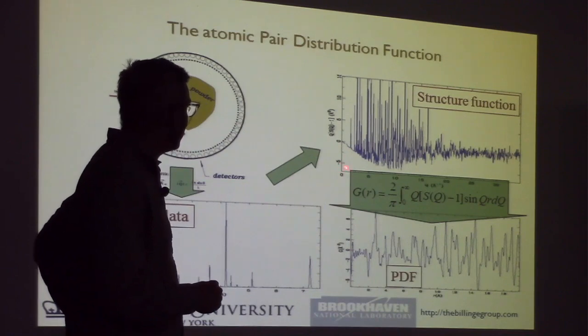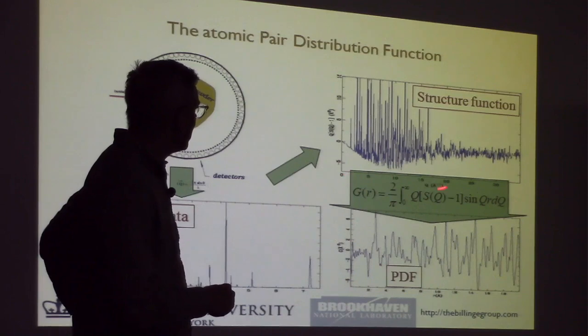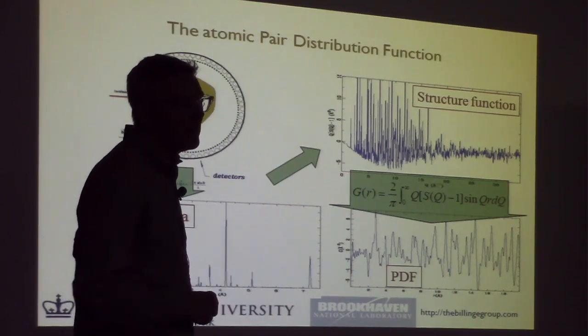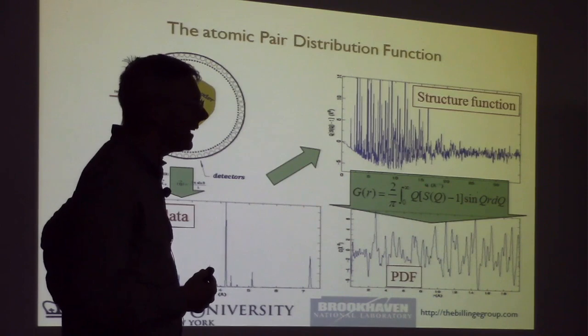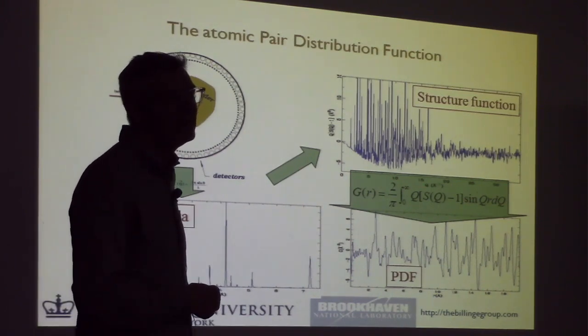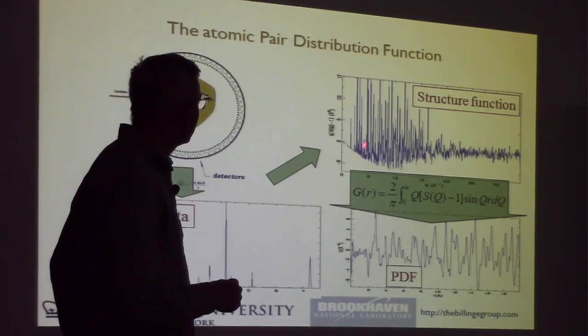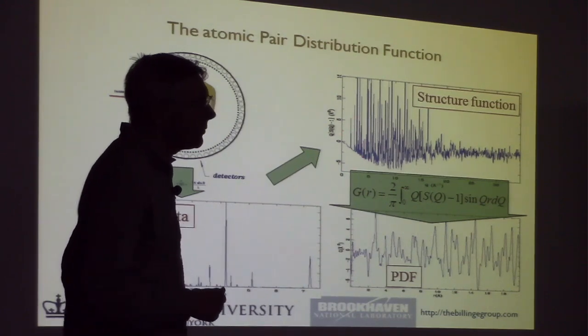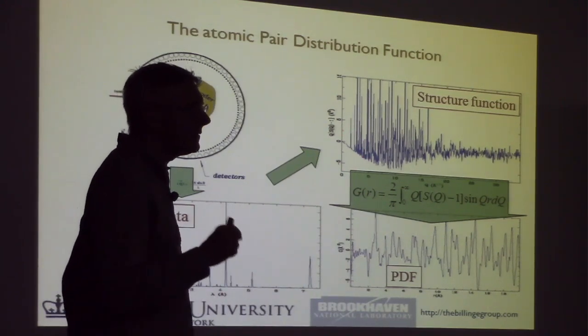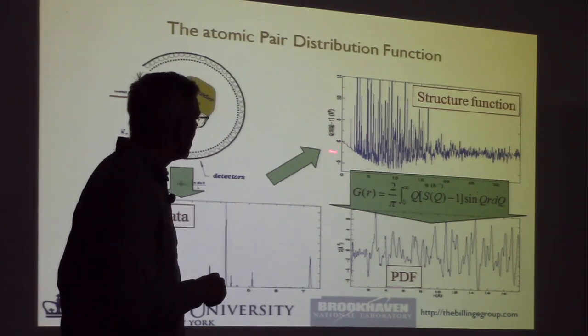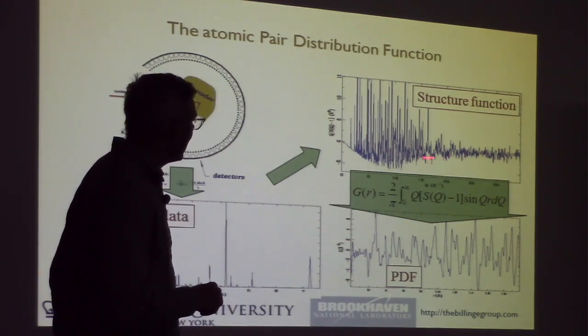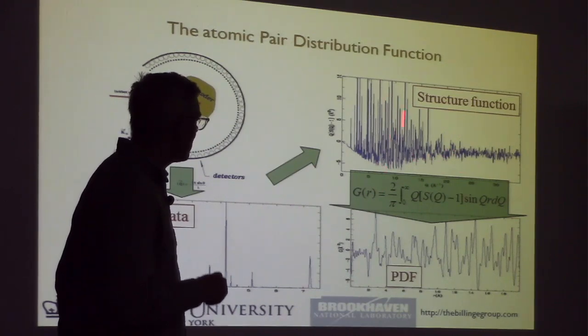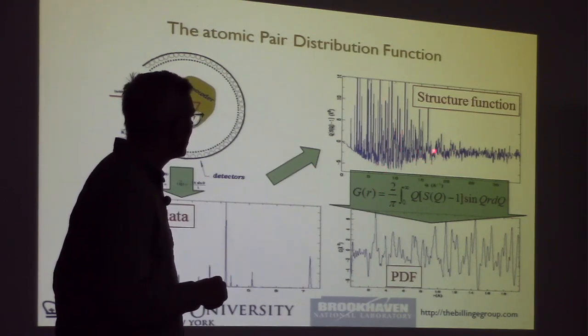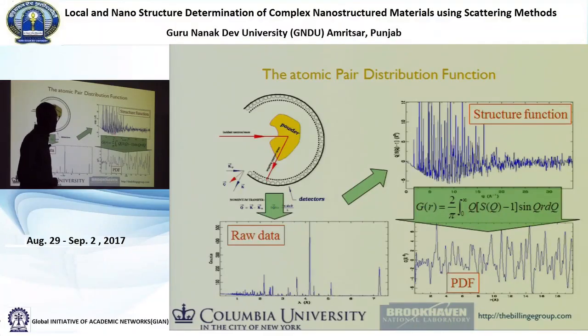But there's two key things. One key thing is that this variable Q is momentum transfer. We measure it up to a very high value, much higher than you would normally measure in your lab. A lab diffractometer, which has copper K alpha radiation, you would only get this little bit down here. So we need special short wavelength, high energy sources to be able to do this. And the other thing is that this contains Bragg peaks. These sharp things here are Bragg peaks. But it also contains diffuse scattering. If you look carefully, there are oscillating diffuse signals.